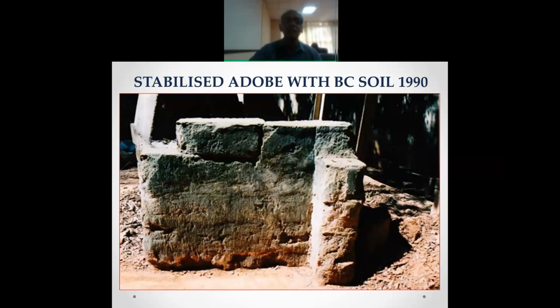10 years later, I removed 3 blocks and tested them. It gave a strength of 1.8 MPa. So the lime stabilized soil gained strength enormously. I have a feeling it will probably have increased over say a 2 to 3 year period. So lime stabilization has all this potential to produce satisfactory walls.